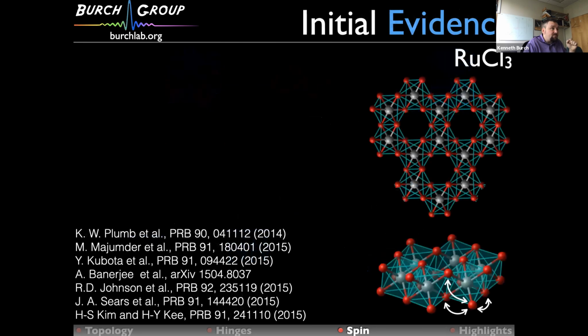So the material that we've been looking at for a number of years now, which is believed to be close to this limit, is ruthenium trichloride. You have rutheniums on the honeycomb lattice. They are in the D5 state. The chlorines are almost perfect octahedral. They're not perfect. And by the way, it cleaves and exfoliates, so you can imagine getting to a pure 2D limit.